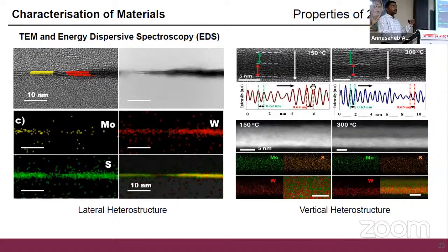In TEM, we basically measure the scattering image, but depending on what mode we use, the brightness can change. If we measure in dark field, it will appear bright; if we measure in bright field, it will appear dark. So we can arrange that, and that's why you need to specifically mention what you are measuring if you ever report this kind of images.